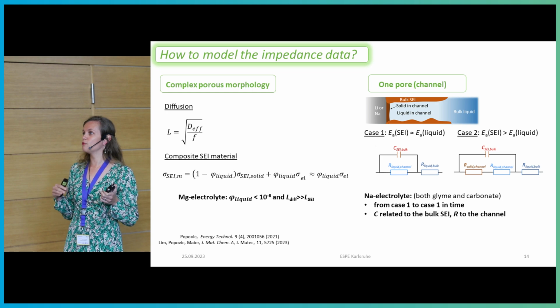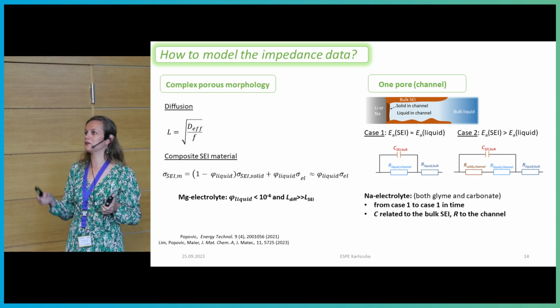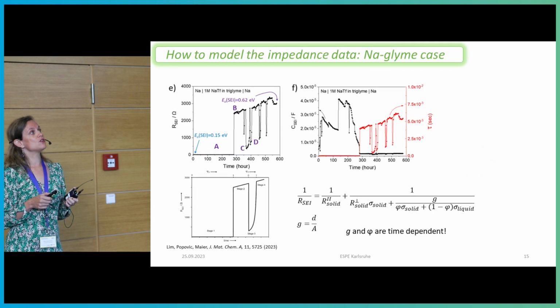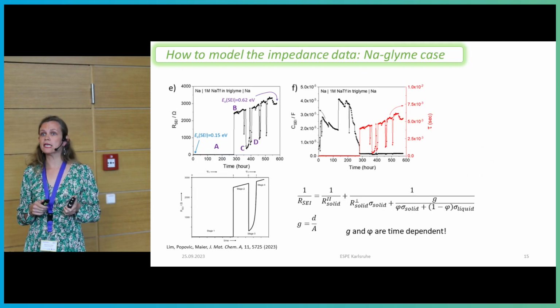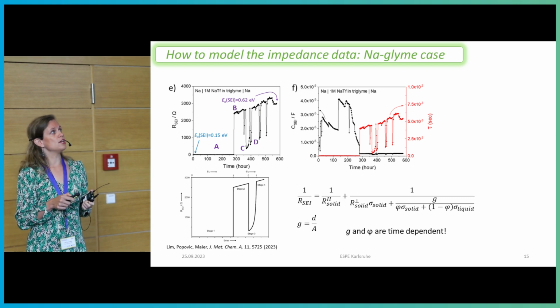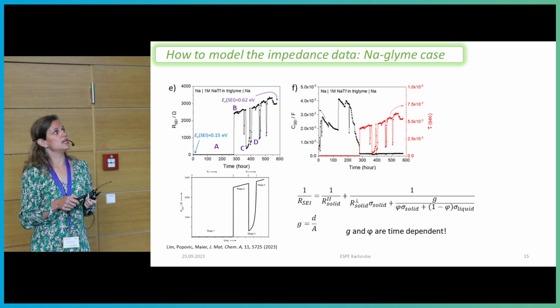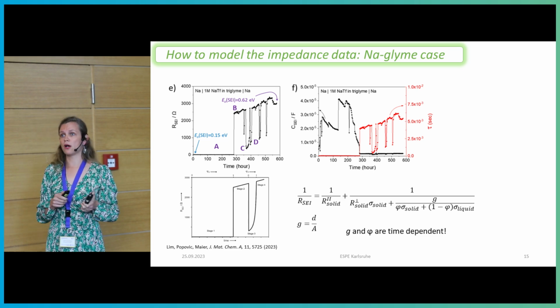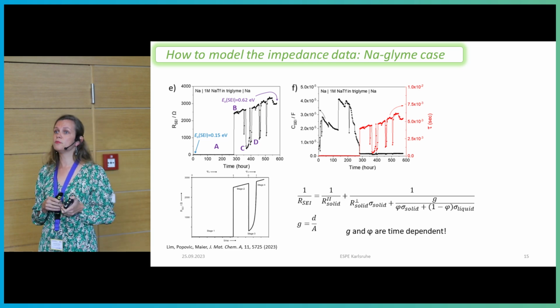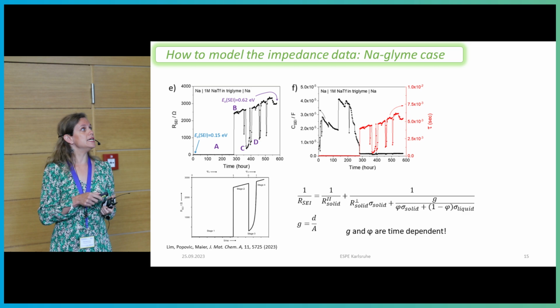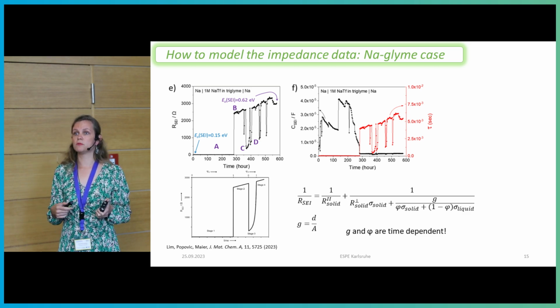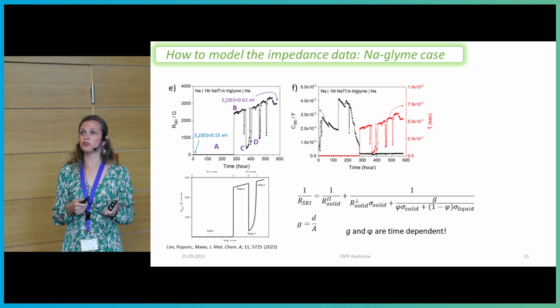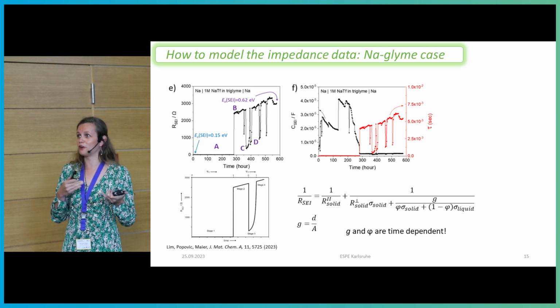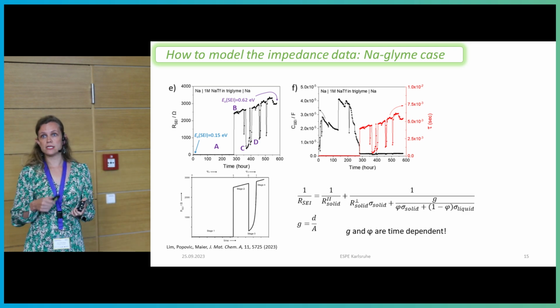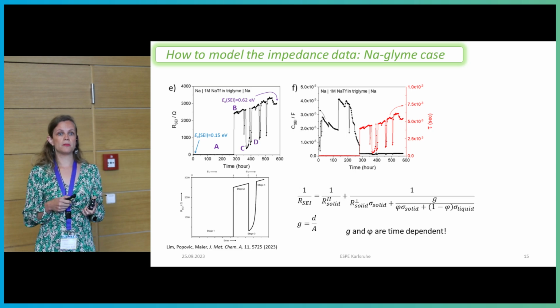And this is why it was kind of confusing, the capacitances that we were getting from this one single semicircle since mid-90s. And then the question of this sodium-glyme case was puzzling us for many, many years. We've seen this strange behavior with very low resistance of the SEI for quite a long time, and then these kind of strange jumps. And this was an electrochemist's nightmare, of course, seeing this and reproducing this many, many times and trying to understand what this is actually corresponding to, and that this is not an artifact of our measurement. But we are quite confident that this is really the real behavior of this sodium-glyme system.